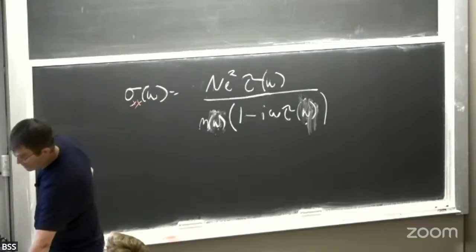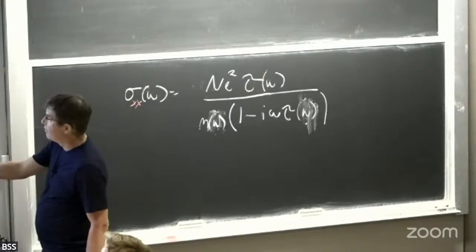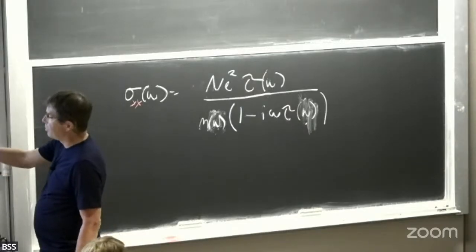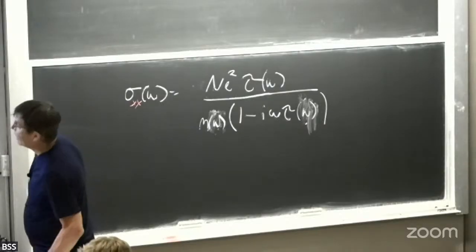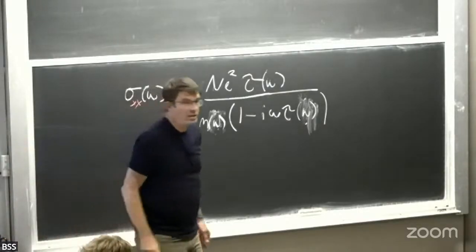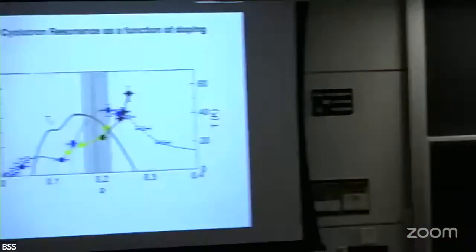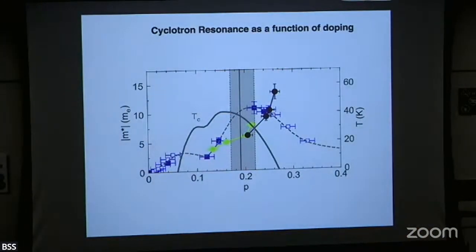And so you can look at that shift of the cyclotron frequency as a function of magnetic field and pull out the cyclotron mass. And it has this very interesting dependence as a function of magnetic field, quite different than what I had implied yesterday with that plot of the mass got from inertial measurements, something proportional to mass, from heat capacity.